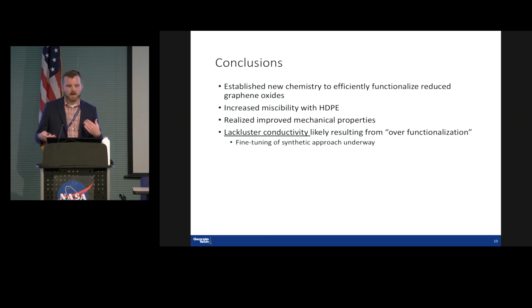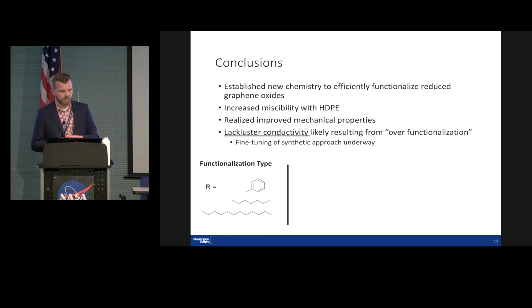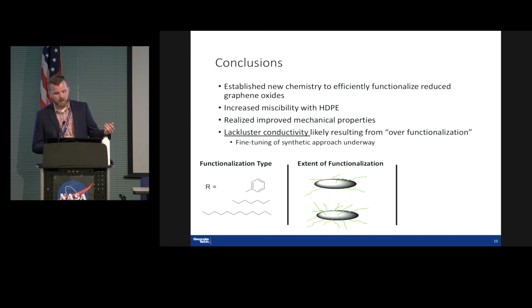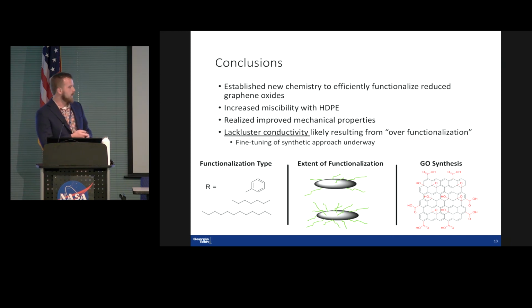And so right now, I have a reaction going in the lab that is looking at different ways we can modify this with different functionalizing reagents. So I used dodecyl chains. Maybe we could use hexyl or something smaller. We can also vary the extent of functionalization, so the amount of these chains that I grafted onto the graphene oxide. And then I can also look at the different ways there are to prepare the graphene oxide itself. There are a variety of functional groups here, if anybody's interested in this type of chemistry, and we can change the ratio of these, which opens up new doors to different types of chemistry. As a preliminary attempt, we went with the one that gave us the most oxidation and the most functional groups to work with. And so we have a lot of opportunities here as well.